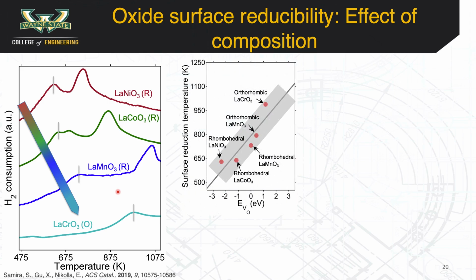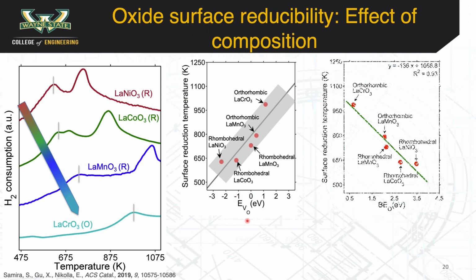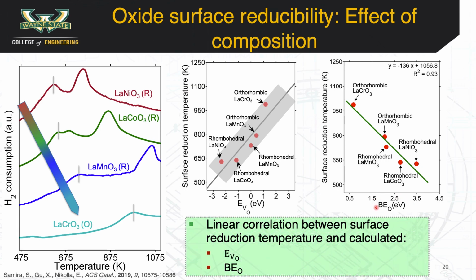What is also interesting is the surface reduction temperature scales linearly with the theoretically calculated oxygen vacancy formation energy as well as the theoretically calculated binding energy of oxygen. Therefore, all this suggests that one can then use an inherent oxide property such as the metal oxygen bond strength as described by the surface oxygen vacancy formation energy or the surface reduction temperature to describe the electrocatalytic activity.